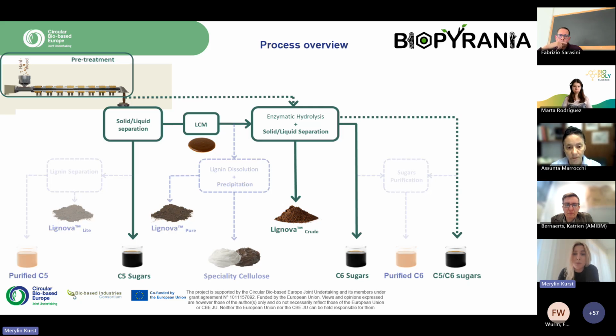So we start with hardwood chips. Then the material goes into the pre-treatment line. In this pre-treatment line, we break down wood in about 30 seconds. Like we all know, wood consists of cellulose, hemicellulose, and lignin, and these are normally tightly bound. But in our process, we are able to separate them. And the result is a thick slurry. And the slurry splits into the liquid phase, which is C5 sugars, hemicellulose, and the solid phase, cellulose and lignin.